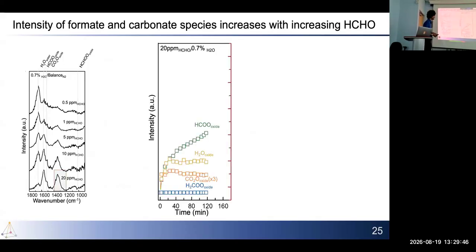We quantify this as a function of time. What we see is that the carbonate peak forms initially and then plateaus off. Same with the water. And it is this formate peak which tends to increase with time.